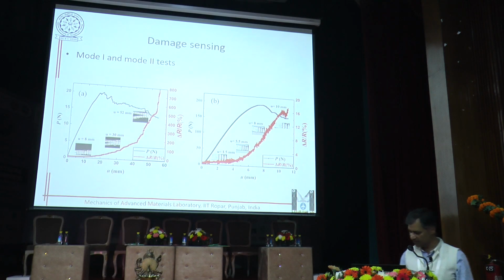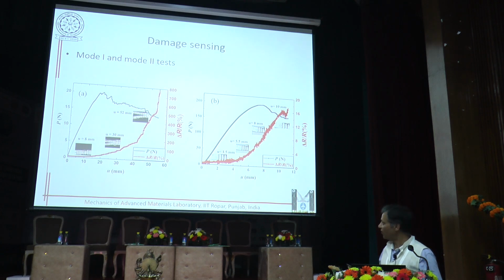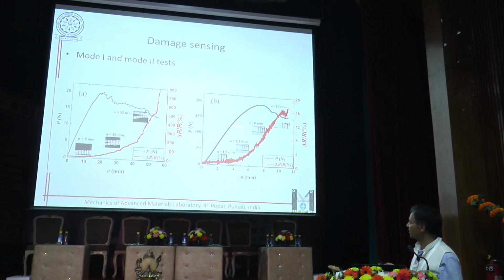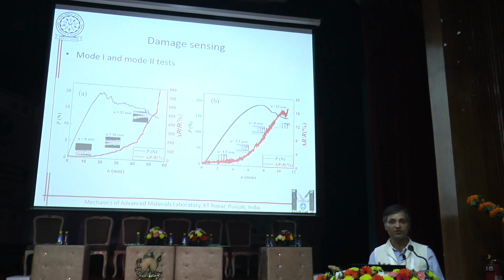Okay, then we looked at the damage sensing, right? We have done two tests: this is under mode 1 and this is under mode 2. This is quite interesting. What we have plotted here is the change in resistance normalized by the base resistance, as a percentage. As you apply the load or the displacement, the load is increasing, and initially there is no significant change in resistance, but then it builds up. This is where the damage coalesces or evolves. At this point there is a sudden jump in the resistance, which marks the propagation of the crack inside the sample, meaning there is a sudden failure in the system. The same thing happens in the mode 2 analysis. So this gives us a way to monitor the size of the crack inside the system. This is one of the objectives that we wanted to achieve.